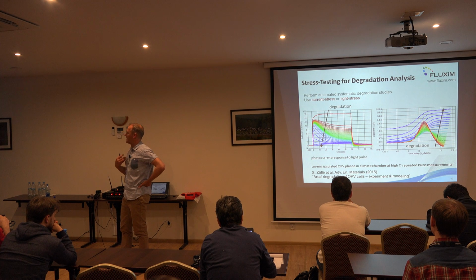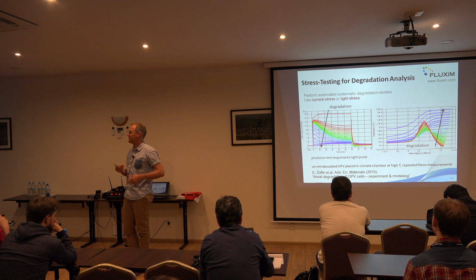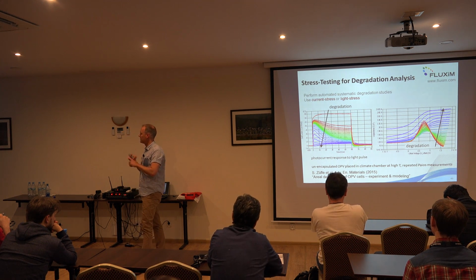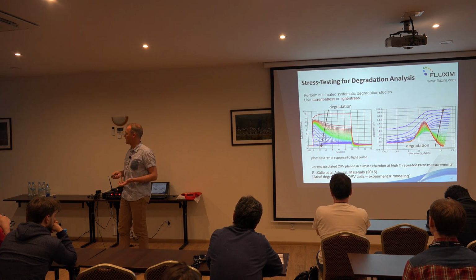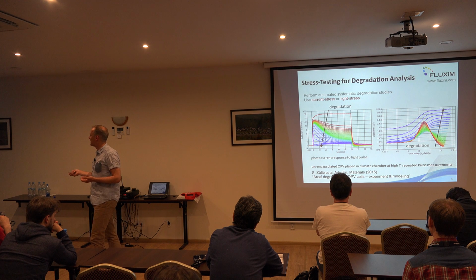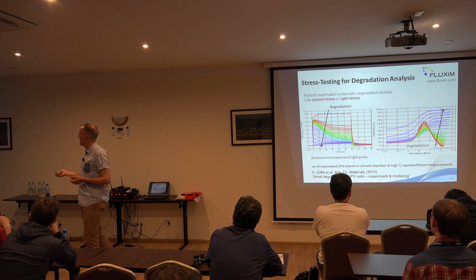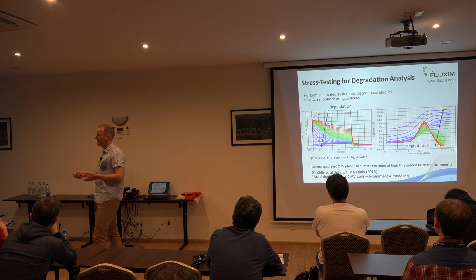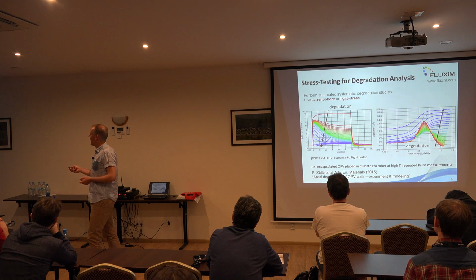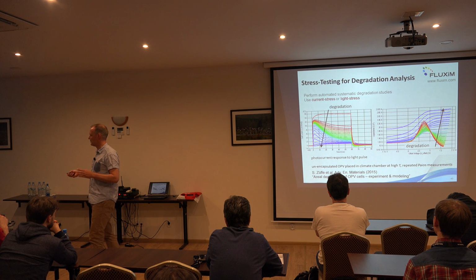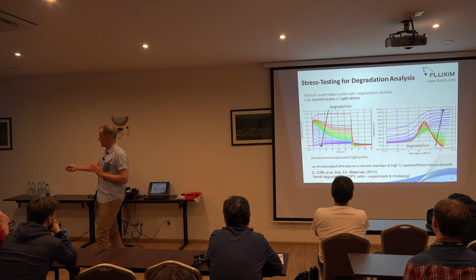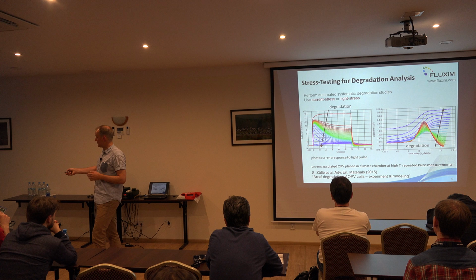And in terms of degradation, you can imagine that this kind of combined measurements of steady state, transient, and even impedance, you can repeat it at different degradation states. This was a study done with an organic solar cell in a climate chamber at high humidity, high temperature. Unencapsulated OPV, so degradation happened within 1 or 2 days. So every 10, 20 minutes, we remeasured.